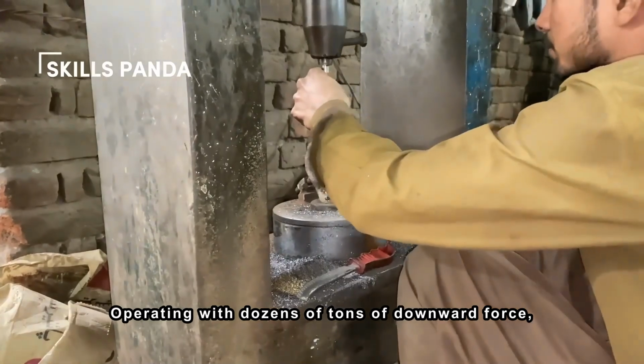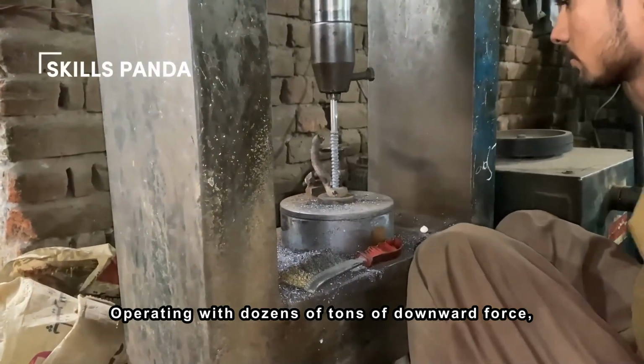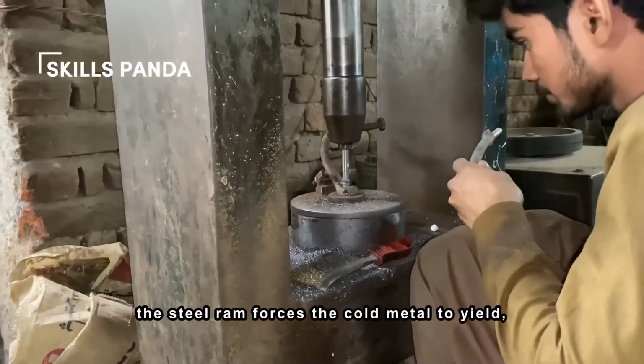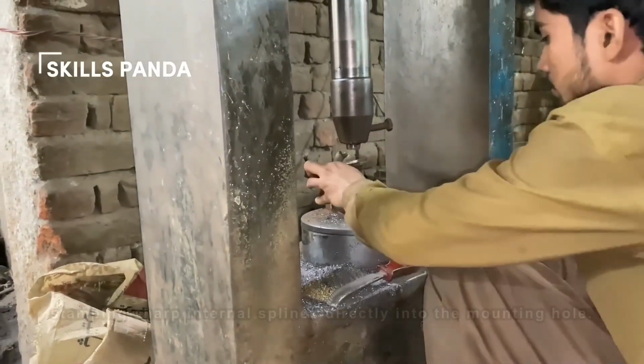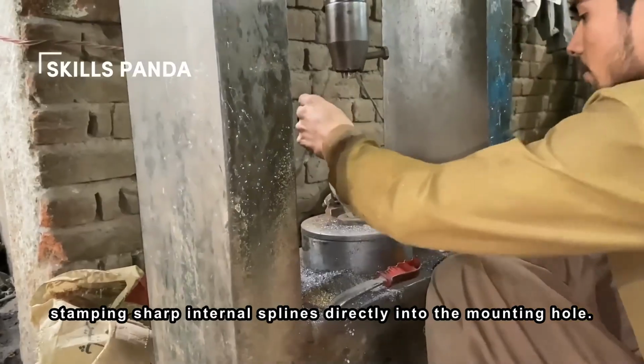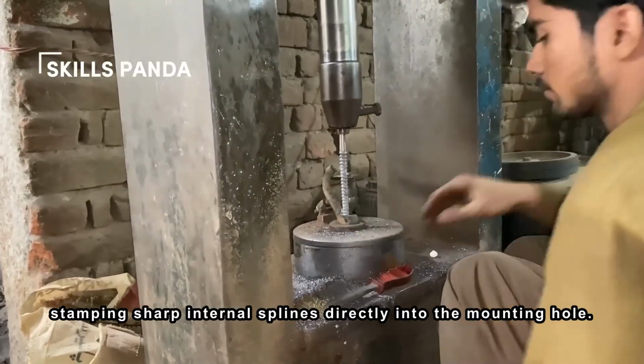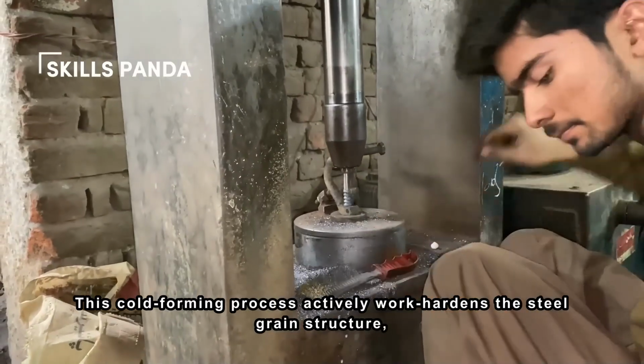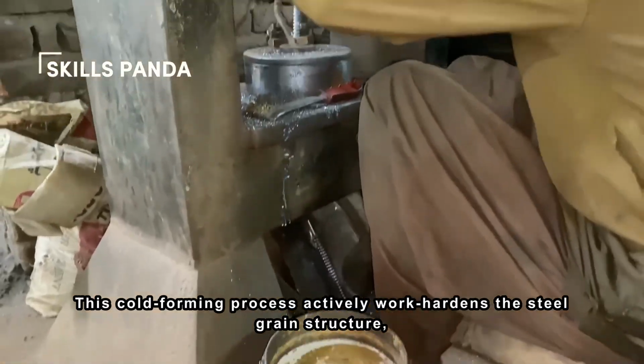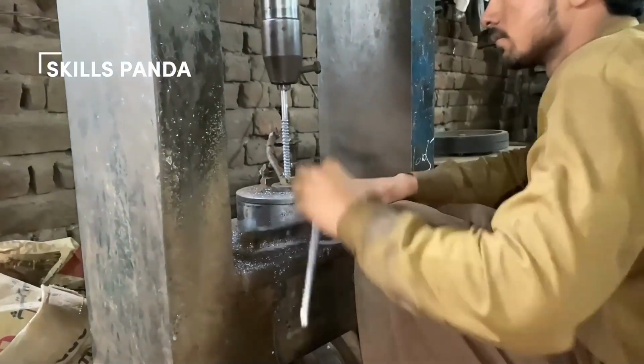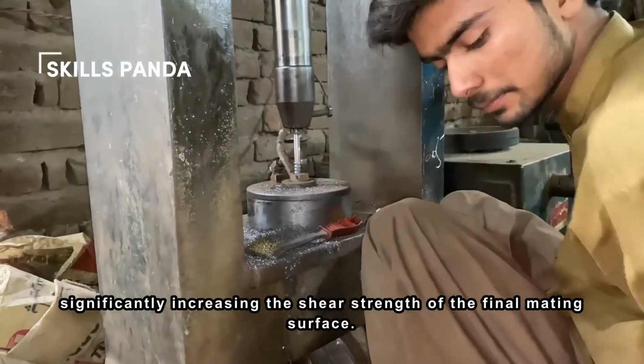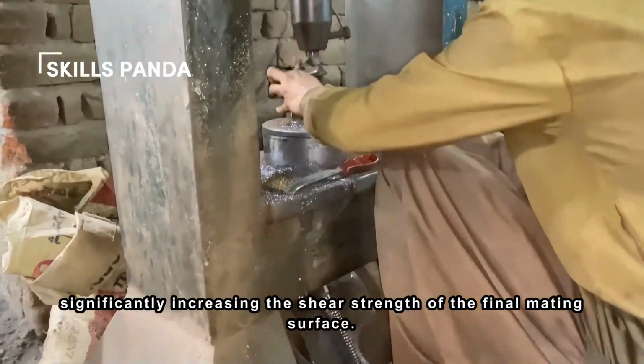Operating with dozens of tons of downward force, the steel ram forces the cold metal to yield, stamping sharp internal splines directly into the mounting hole. This cold-forming process actively work-hardens the steel grain structure, significantly increasing the shear strength of the final mating surface.